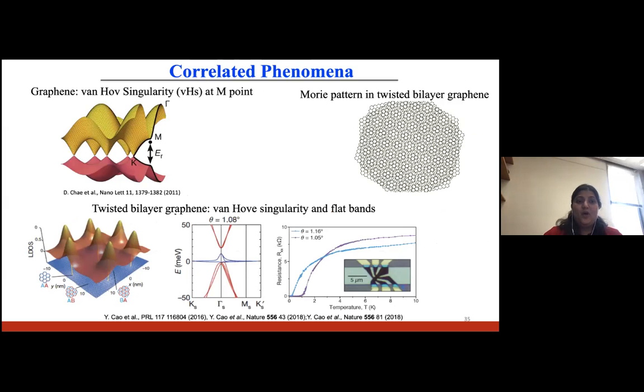Okay, so the Van Hove singularities we know are of interest, especially if the Van Hove singularity is close to the Fermi energy, as we then have an increased density of states, and this can result in enhanced electron correlations. It can trigger ordering instabilities such as superconductivity or even charge density waves at low temperature. And in graphene, the Van Hove singularity at the M point is so far away that it is not possible to reach it in transport measurements using electrostatic gating.